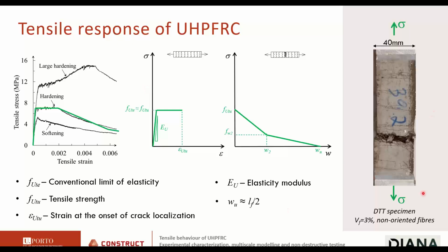If we have the same material, the same amount of fibers, but now they are not oriented according to the loading, they are randomly oriented inside the specimen. What do we see? A dramatic change in the tensile stress versus tensile strain behavior.